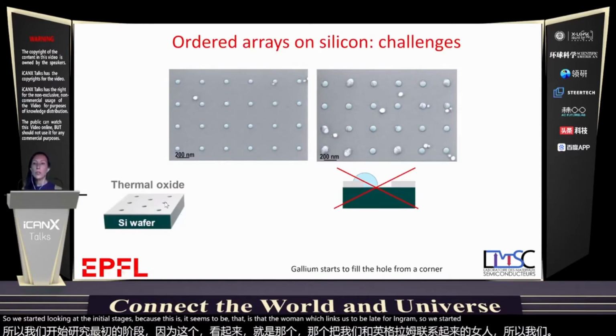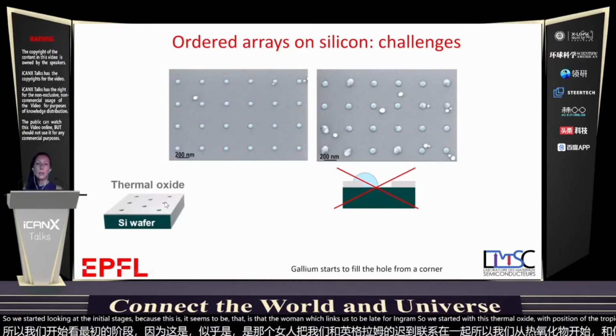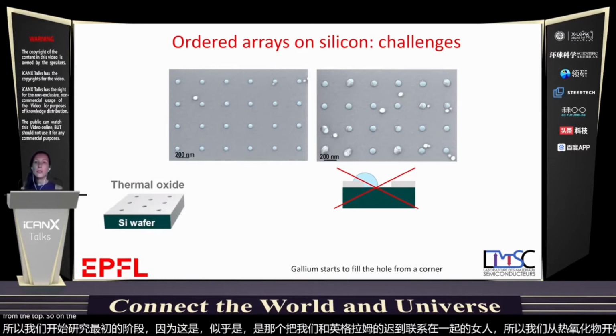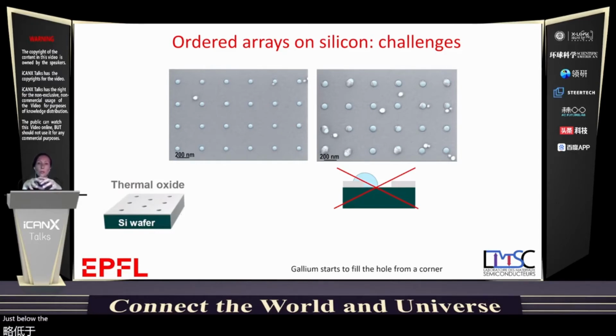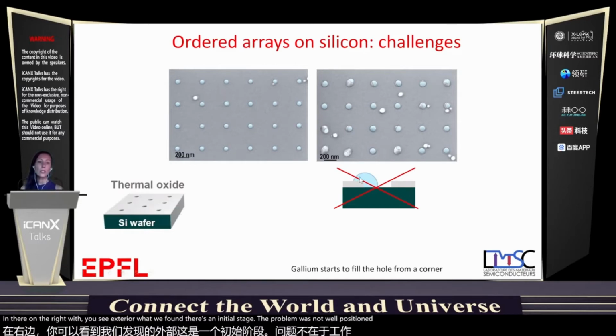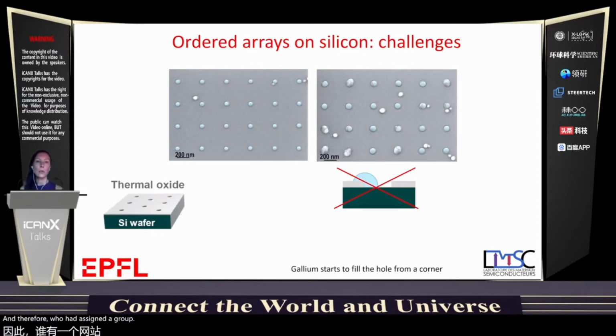So we start with this thermal oxide, we position the droplets, and then we start looking at the initial stages. And this is a view from the top. On the left, you see that these droplets are still, even though there is growth, you don't see anything because the nanowire grows just below the droplet, in the shadow of the droplet. On the right, at the initial stage, the droplet was not well positioned in the hole, and this led immediately to nucleation on this side, and therefore you had a side growth of the nanowires, and you can already see it after a few minutes of growth.